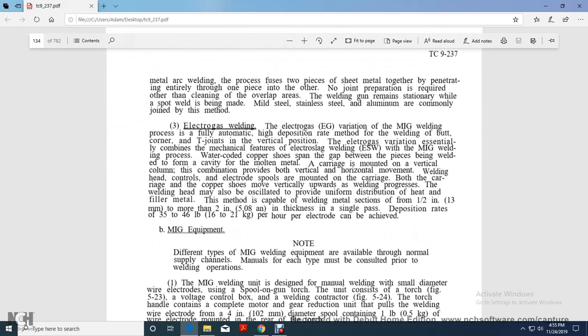Electrogas welding. Electrogas is a variation of the MIG welding process, a fully automatic, high deposition rate method of welding butt or corner T-joints in the vertical position. The electrogas variation essentially combines mechanical features of electroslag welding with the MIG welding process. Water-cooled copper shoes span the gap between the pieces to be welded, forming a cavity for the molten metal. A carriage is mounted on a vertical column, provided with vertical and horizontal movement. Welding head controls and electrode spools are mounted on the carriage. Both the carriage and the copper shoes move vertically upward during the welding process. The welding head may also be oscillated to provide uniform distribution of heat and filler. The method is capable of welding metal sections from 1/2 inch to more than 2 inches in thickness in a single pass. Deposit rates of 35 to 46 pounds per hour of electrode can be achieved.